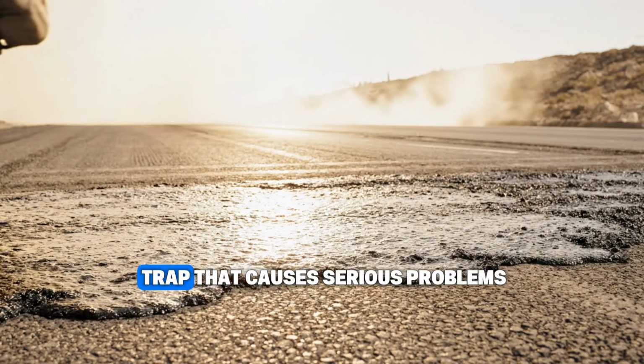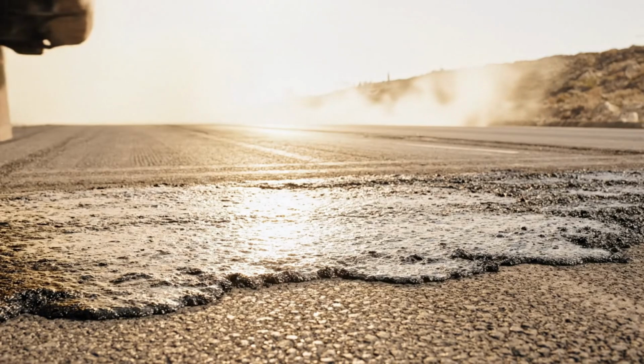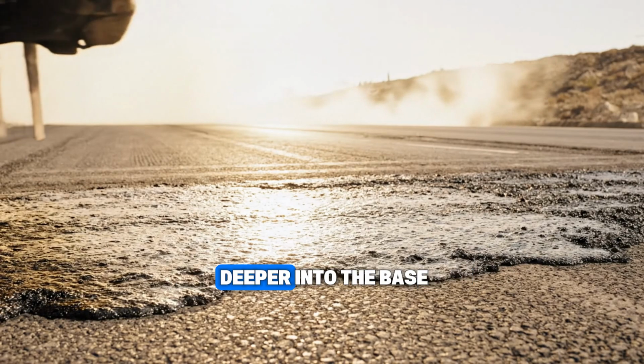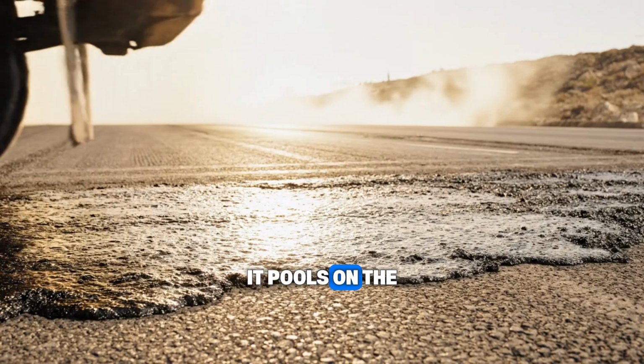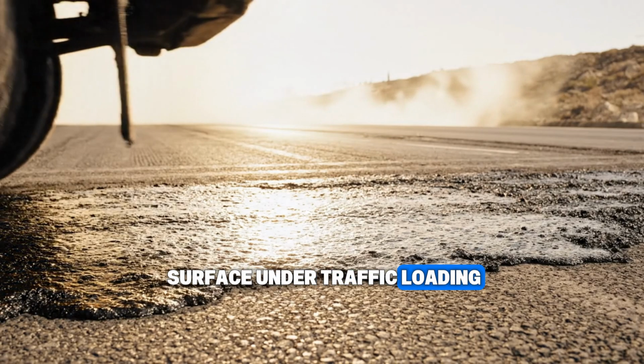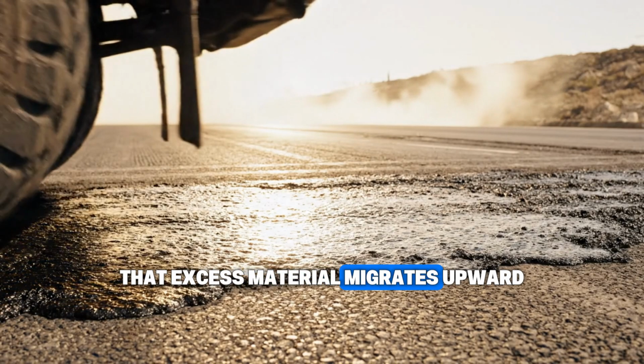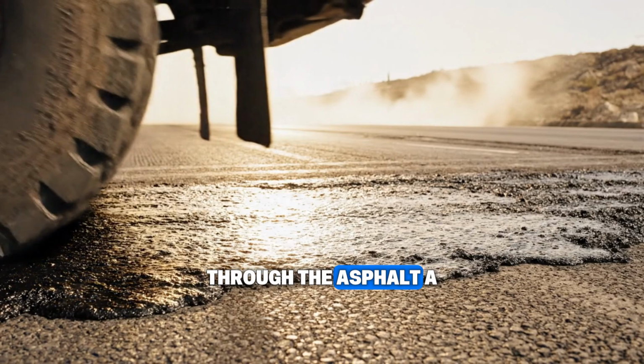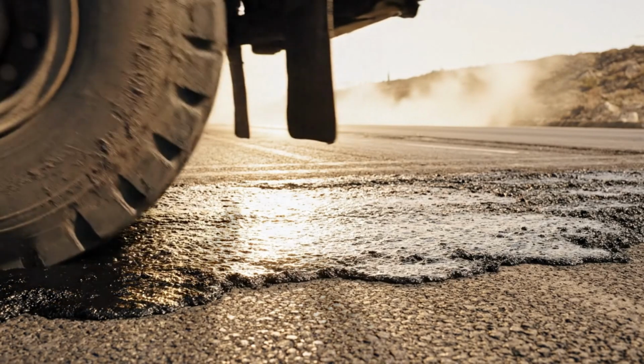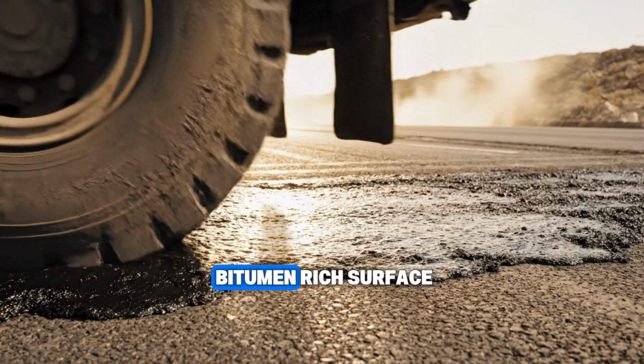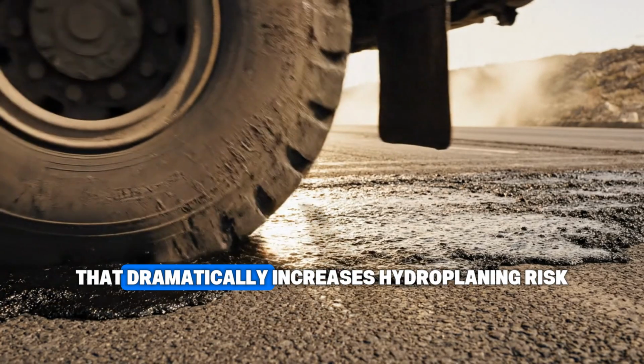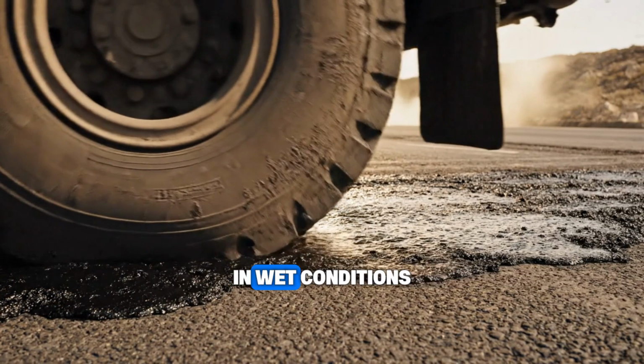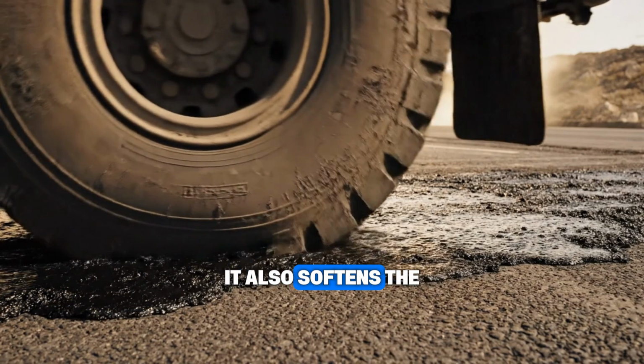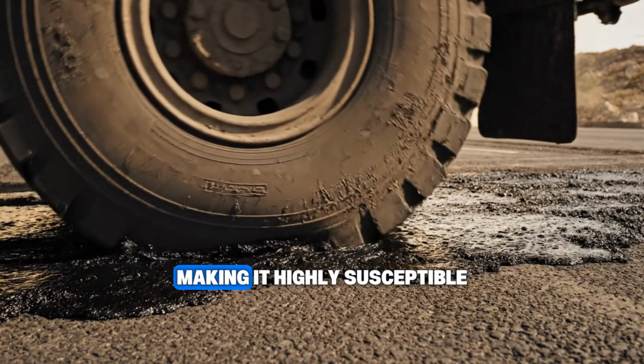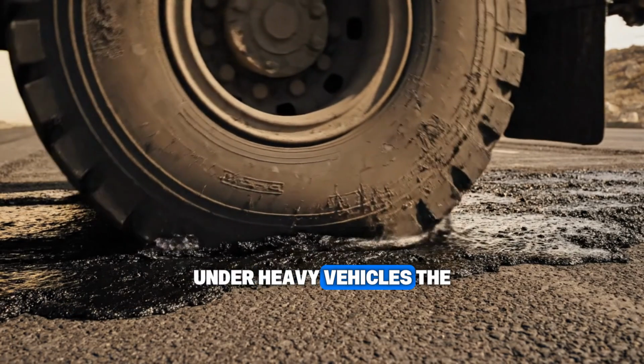This is a logic trap that causes serious problems. Excess bitumen doesn't bond deeper into the base. It pools on the surface. Under traffic loading, that excess material migrates upward through the asphalt, a process called bleeding. Bleeding creates a slick, bitumen-rich surface that dramatically increases hydroplaning risk in wet conditions. It also softens the pavement under heat, making it highly susceptible to rutting under heavy vehicles.